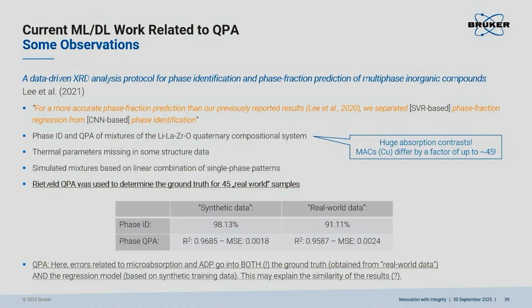So the microabsorption error is one of the most troubling residual errors we have in quantitative phase analysis. And by the way, have a look at the samples here. Lithium, lanthanum, zirconium oxide. Here we have differences in the mass absorption coefficients for copper by a factor of up to 45. I told you, you can see microabsorption effects already by a difference by a factor of 2 or 3. So machine learning for quantitative phase analysis, I do not see it happen.